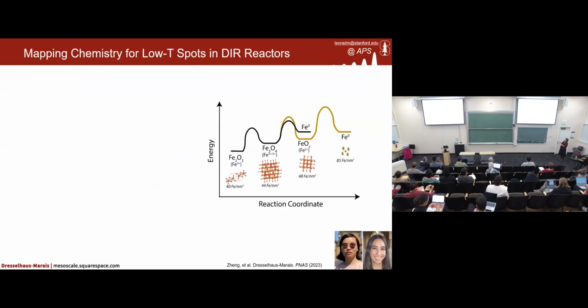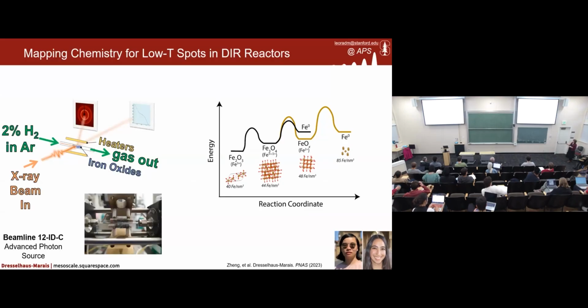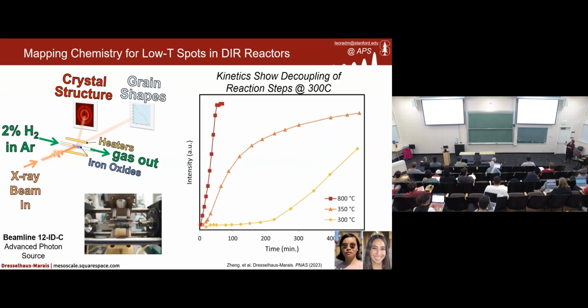So armed with that, we then went to understand a little bit more about how the phase transitions progress, i.e. the chemistry. And we were able to do that using an X-ray based operando experiment, where we could study with our X-ray beam information about the crystal structure, so the phases that are generated, as well as the grain shapes, i.e. are we sticking and smooshing together, or is this evolving in some way, still as the powder? So with that, we can start off by looking at the kinetics of the process,